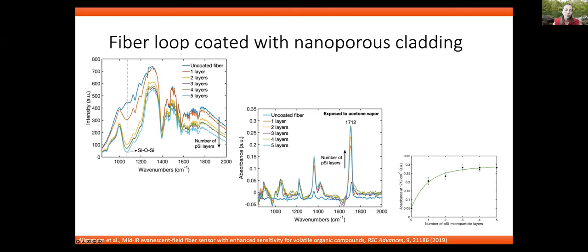And there can be two reasons for this. One reason is that the particle thickness is already so thick that the diffusion is more difficult, or it could be because as you add more and more, the evanescent field is only 1 micrometer, say, close to the surface. So adding thicker layers gives no more benefit. So this shows the importance of optimizing also the thickness for any optical coating for fibers.